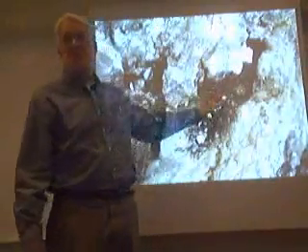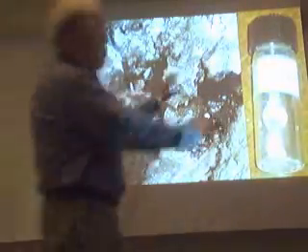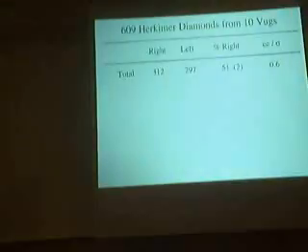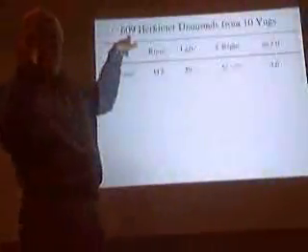And the dolomite we broke up, and we found in it pockets which had quartz crystals, and even better were pockets that had many, many small quartz crystals for purposes of statistics. So there are right-handed crystals from one hole, and then what we had to do was open new holes. So we got them all from one hole, and things like that. And we had to then put each of these crystals into hydrofluoric acid to etch them, study them under a microscope to see what hand they were. And so there were, in all, we did 609 of those little crystals, right? 312 right, 297 left. It's only 0.6 sigmas, so 50-50.